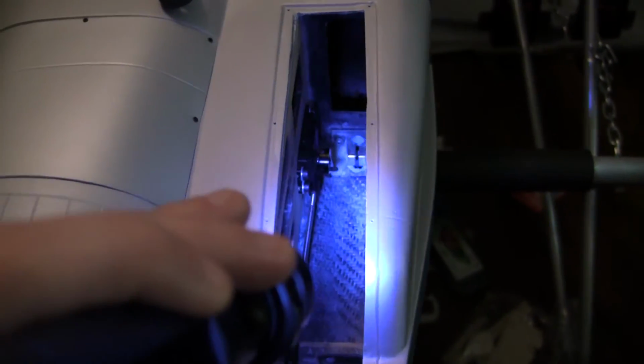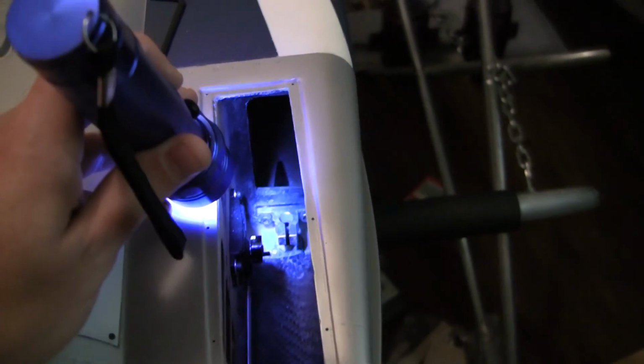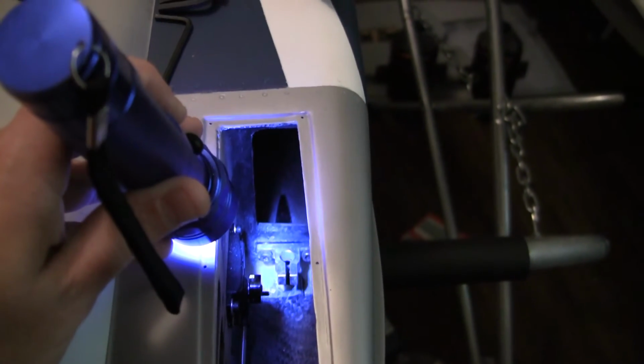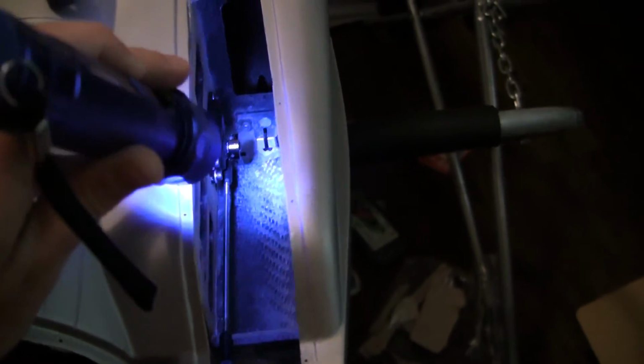So I am going to fix that before I go any further. What I did on one side, and it seems to tighten up really nice, is I put an aluminum spacer between that wood back plate and the actual metal bracket, and it goes through that honeycomb wall. So when you tighten it down, the bracket puts force on the spacer and not the actual honeycomb. I'm going to glue my rudders on, so these clamps are just going to be a security, to help secure it in place while it's glued, and then I'll leave them in there once they're glued on. That way they're tied into these bulkheads, like they should be normally.